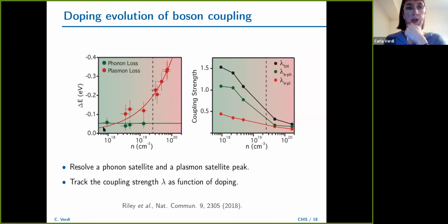From the experiment, it's not really possible to extract the mass renormalization parameters because there is not enough resolution, but we did it from the theory. And you can see this is the total electron-boson coupling strength. And this is the one due to the electron-phonon coupling alone, and this is due to the electron-plasmon coupling alone. So you see there is the same behavior as before.